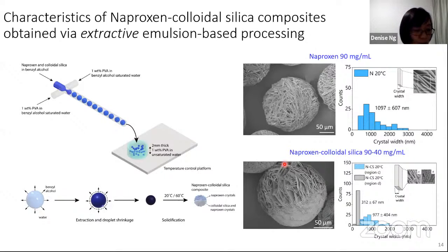Next, we also note that the evaporative emulsion-based technique may not be applicable to heat-labile drugs, especially in cases where the dispersed phase is a non-volatile solvent, such as water, where heat is needed to actually accelerate the process. Hence, we also developed an extractive emulsion-based processing technique. So here, what I have done is to use benzyl alcohol and water as our emulsion system. And here, naproxen is used as our model hydrophobic drug. And likewise, colloidal silica was also surface modified using APTS.